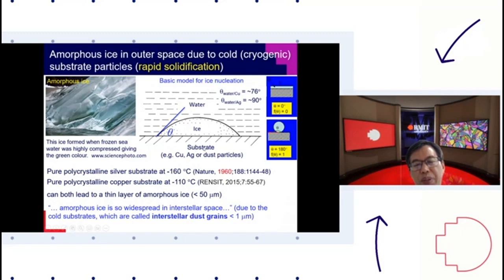This substrate material can be any material, and this contact angle is important. Unless this contact angle is 180, which means that they're not in contact with each other, this substrate material, whether it's a dust particle or metal surface, will be effective to promote the formation of ice crystals. Silver iodide has a very small contact angle. The smaller the contact angle, the better the efficiency of the substrate material to promote ice crystallization.